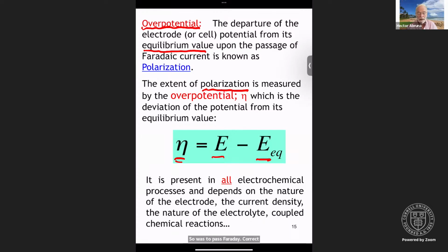If your process is inherently fast, then reaching a given current density, which is a rate, will require a small overpotential. If, on the other hand, you have a big barrier, in order to get any current you need to apply a significantly large overpotential to be able to drive that reaction at whatever rate you desire. Without a doubt, the overpotential is present in all, and I mean all, electrochemical processes. It depends on the nature of the electrode, the current density, which is the rate, coupled chemical reactions, anything and everything that's involved in an electrochemical process will be involved in the overpotential.